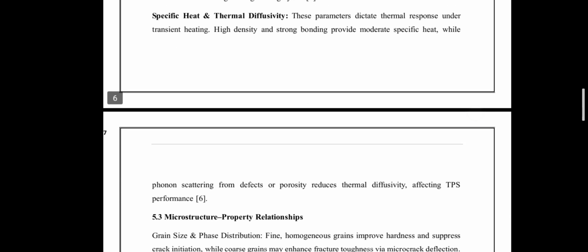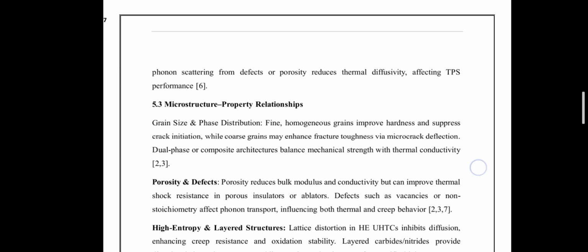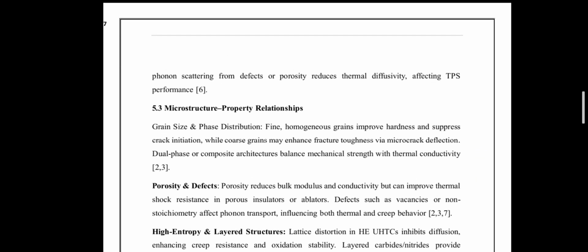The next is the microstructure. The microstructure property relationships involve grain size, phase, and porosity. Microstructure strongly dictates performance. Fine, homogeneous grains enhance hardness and suppress crack initiation, while coarse grains may improve toughness through microcrack deflection. Dual phase and composite systems balance strength, toughness, and thermal conductivity. Porosity reduces modulus and conductivity but can improve thermal shock resistance in ablative and insulating components.